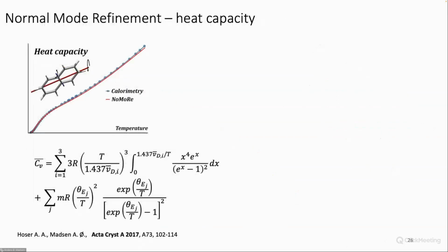Okay, now this approach of using these frequencies from this normal mode refinement, we have used that in many other cases, in particular for estimating the heat capacity of different small molecule crystals, using this rather complicated formula down here. But the take-home message is basically up here, that we can compare our derived heat capacities with the heat capacities from calorimetric measurements, and they compare quite well.